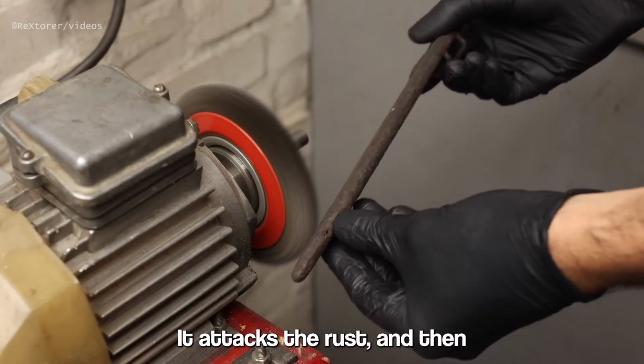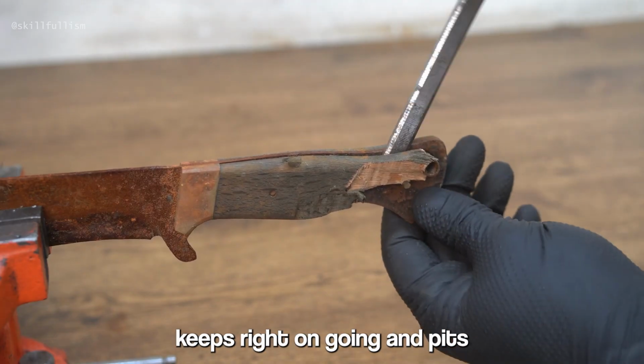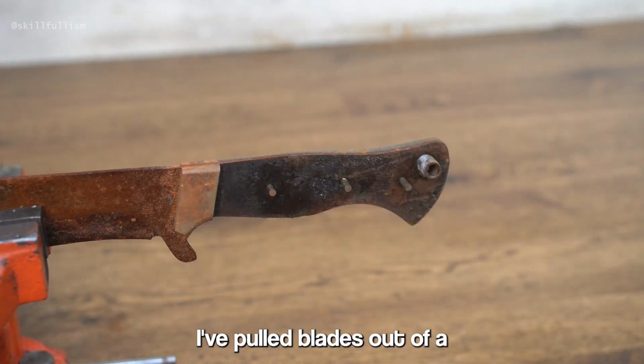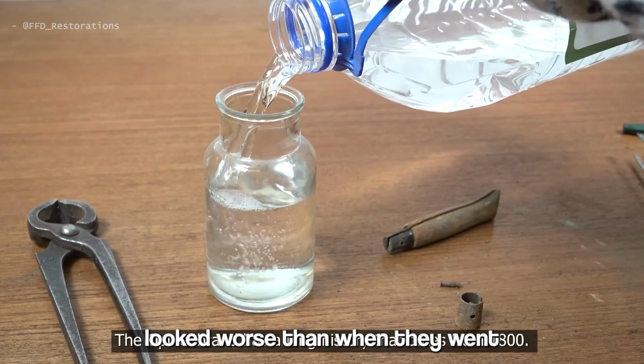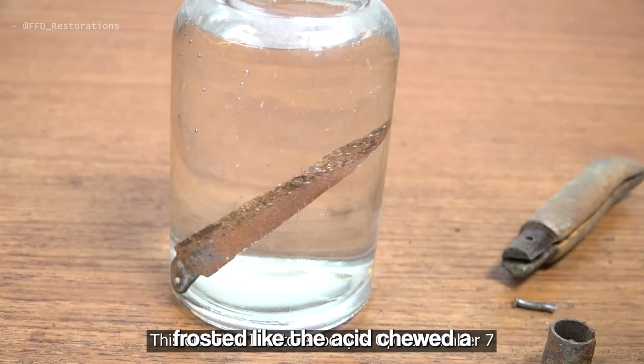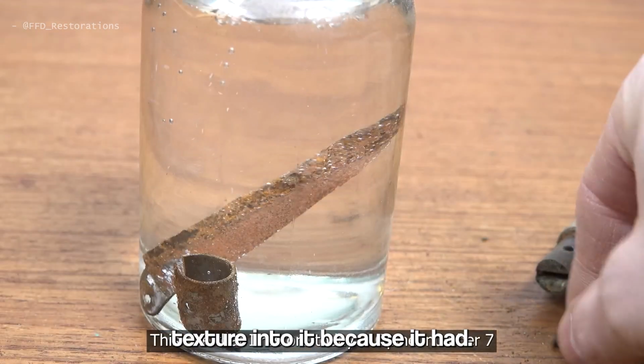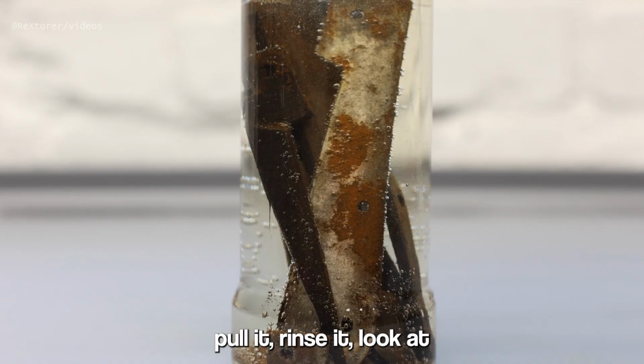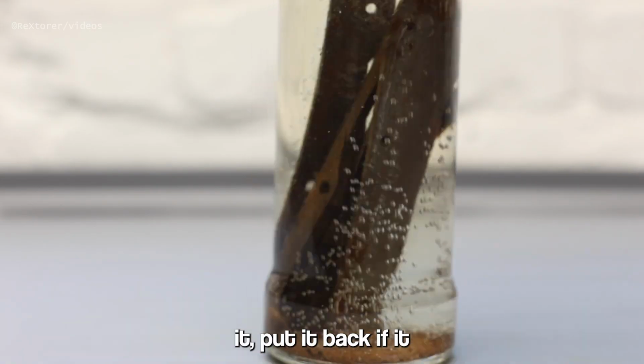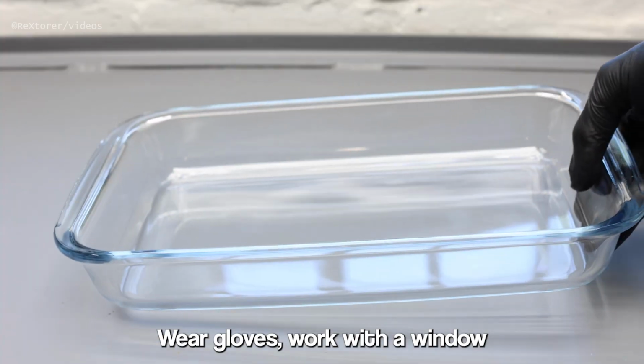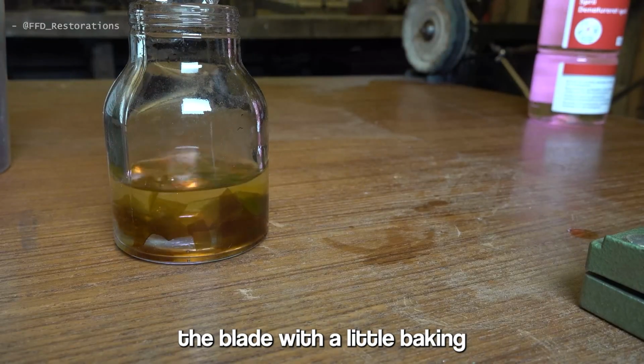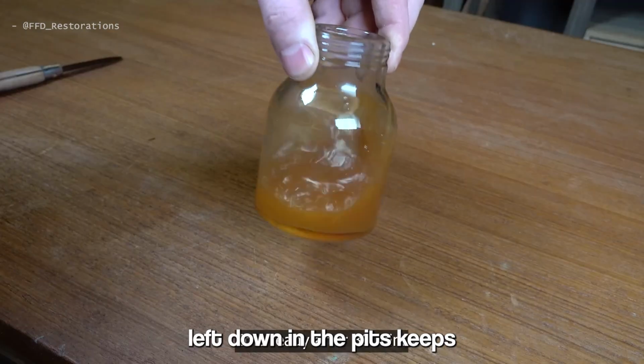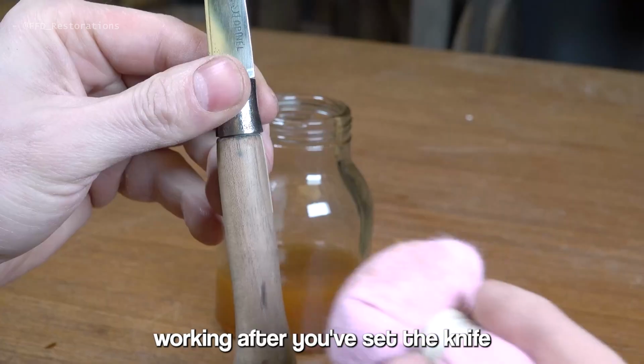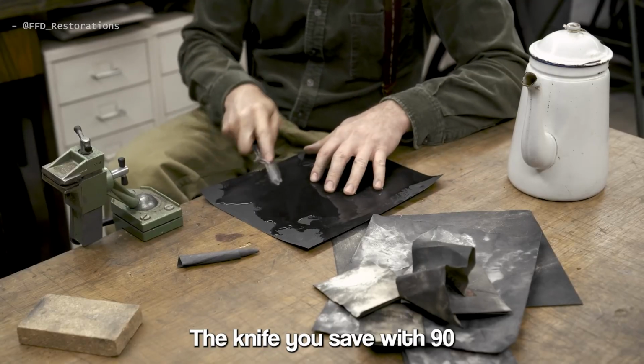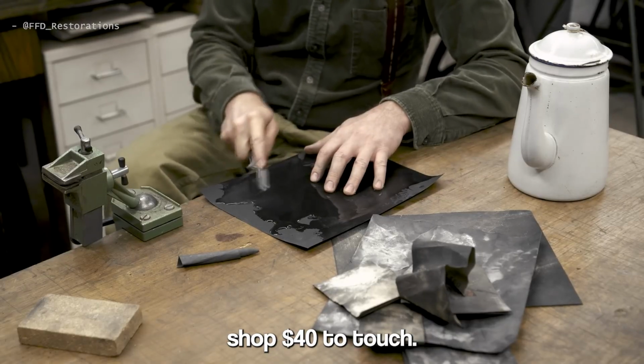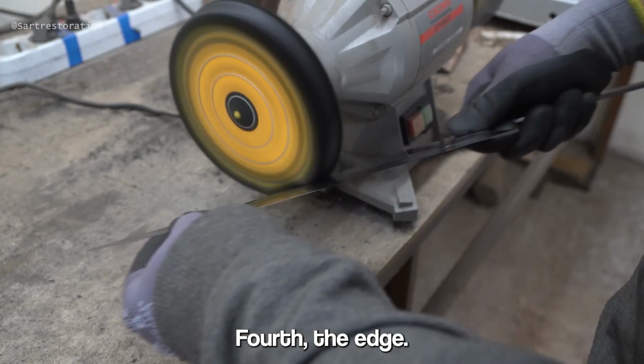It attacks the rust, and then when the rust runs out, it keeps right on going and pits your good steel. I've pulled blades out of a vinegar jar in the morning that looked worse than when they went in, the surface gone gray and frosted like the acid chewed a texture into it, because it had. Check the blade every 10 minutes, pull it, rinse it, look at it, put it back if it needs more. Wear gloves, work with a window open, and when you're done, neutralize the blade with a little baking soda and water, because any acid left down in the pits keeps working after you've set the knife down to dry. The knife you save with 90 cents is worth the same as the one you'd have paid a shop $40 to touch. Fourth, the edge.